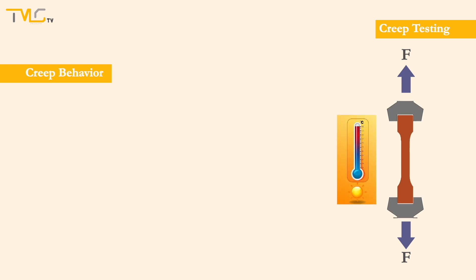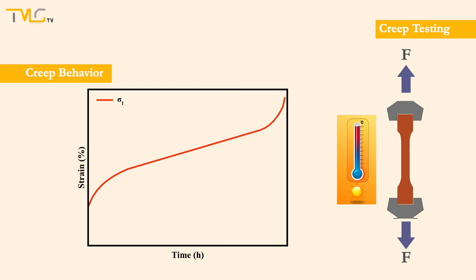But before getting ahead of ourselves, let's get more familiarized with creep testing and time-dependent generalized creep behavior. The engineering creep curve of a material is obtained by applying a constant load to a tensile testing specimen at a constant temperature. Then, the strain of the specimen is determined and plotted as a function of testing time for creep analysis.